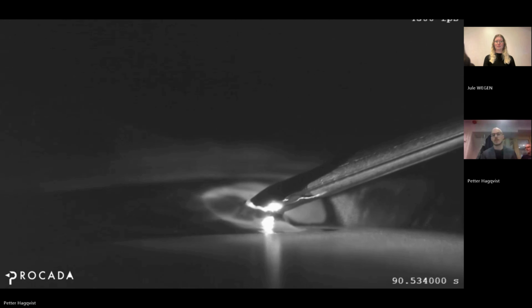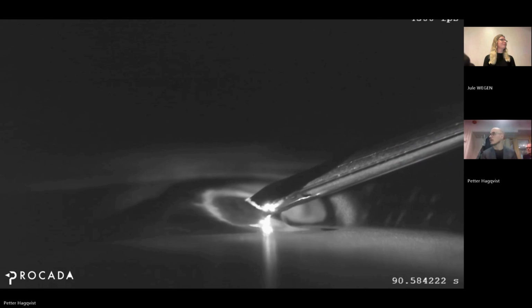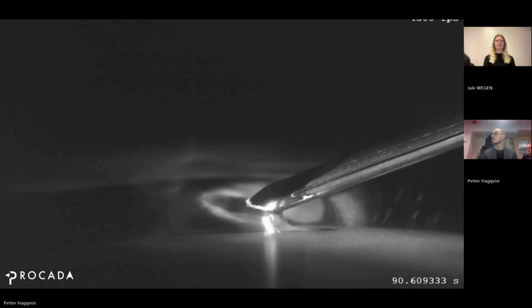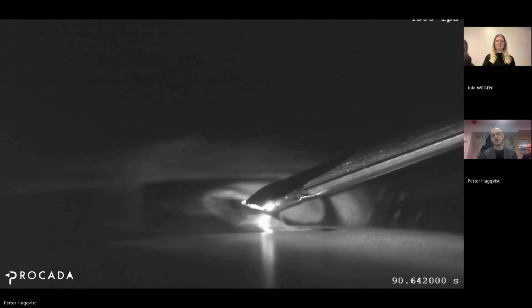So you could see the wire is moving, it's being fed into the melt pool. You could see that it melts on the top. There's a darker shade on top of the wire, but also on the sides, you could see it melting. You see that the melt pool is a bit dynamic. There are waves going back and forth. You could also notice that underneath the wire, what you see is a roundish shape, which corresponds to, let's see